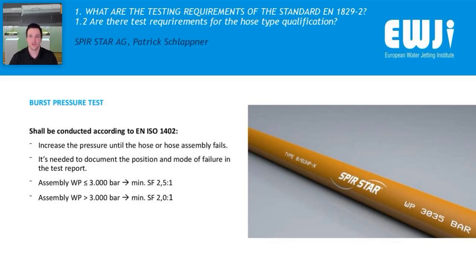Additionally, the burst pressure test is also specified in the EN 1829. Here, the test is conducted to EN ISO 1402 as well. Here, we increase the pressure until the hose or the hose assembly fails. According to the ISO, it's needed to document the position and also the mode of failure in the test report.